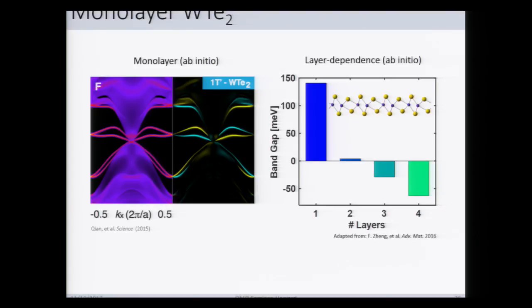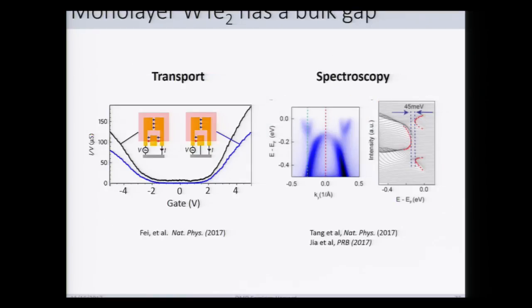But then there was some follow-up work that showed, oh, if you do your ab initio calculations another way, you get a huge band gap for the monolayer, and maybe a small one for the bilayer, and then return to a semi-metallic state at thicker and thicker systems. So there was some disagreement amongst the theorists, and experimentalists, we go and actually do measurements, and there's been a lot of great work, for example, from the Washington group on transport devices, which Sanfeng was also involved in before he came to MIT, and then spectroscopy, both with photoemission and scanning tunneling microscopy, to show that indeed the system is a true insulator.